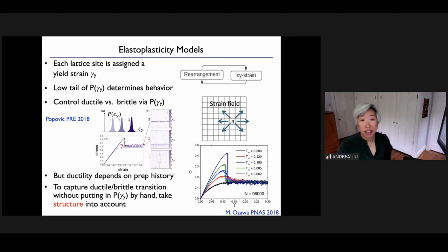But we know that how ductile or brittle a system is depends on how the system was prepared. So here is exactly the same system. These are simulations from Ludovic Berthier's group, where they have polydisperse systems that they can equilibrate extremely well. If you quench from a rather high temperature to zero temperature, you end up with systems that respond in this ductile fashion, the black curve. But if you equilibrate to a very low temperature before quenching to zero, you see this large stress drop, you see brittle behavior. So this is the identical system with identical interactions. The only thing that changed was how it was prepared.